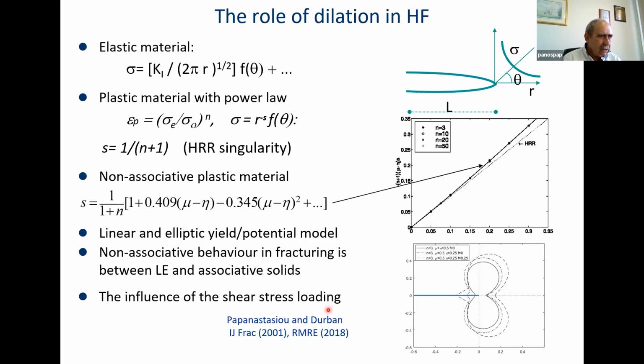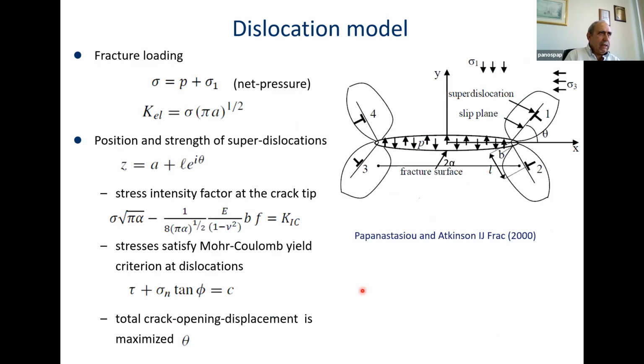And more recently, we did some calculations looking into the influence of the shear stress loading from the viscous fluid. And again, we found the difference it makes is in the emergence of these boundary layers in the stress concentration near the fracture tip. But I will not spoil it further. Let's go to more obvious things.